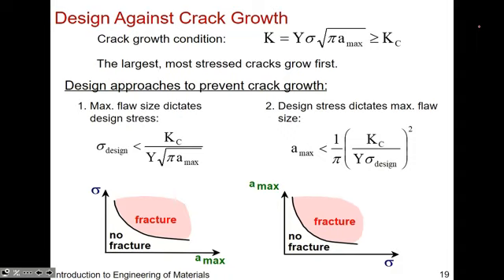So we want to know, will the material fracture, will it not fracture? If you have an applied stress and you know your crack flaw because you've looked at it under a microscope. If your crack is big enough, you could see it under an optical microscope. If it's not big enough, you get into a scanning electron microscope, right? These are the instruments that we use for failure analysis. If it's below this curve, there will not be fracture. So it's a safe area to be operating in.